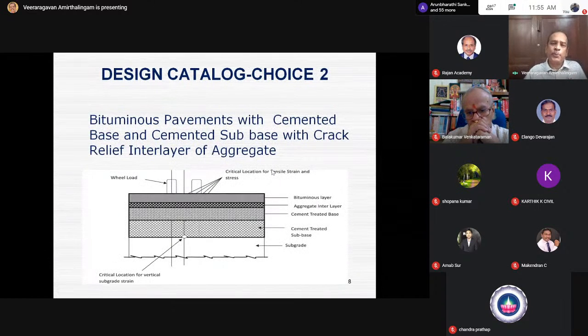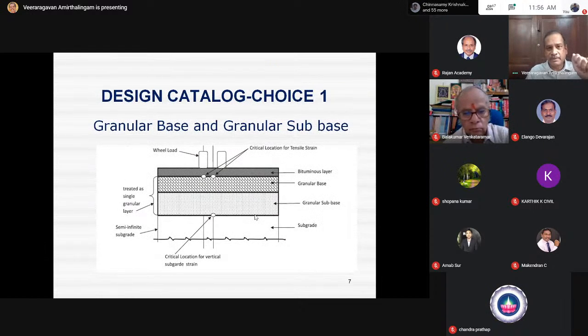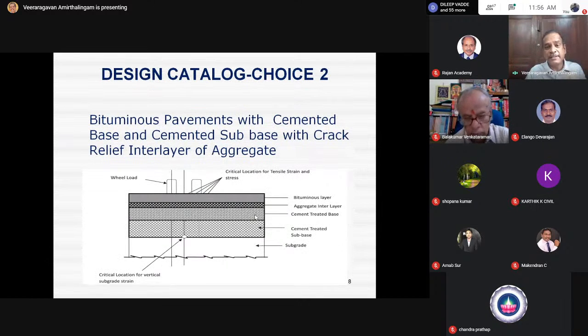I can have an option 2, alternate design, with a cement treated subbase here. I can have a cement treated base here. So if I do this, I know pretty well that when I have a cement treated base, this cemented base will crack. I know that. At the time of design itself, I should know that this layer will crack. But if you provide a thin bituminous layer, because I have a stabilized subbase, I have a stabilized base, the thickness of these layers will be much, much lower than what I have here. So I have now reduced the thickness by stabilizing the subbase, stabilized base as well.